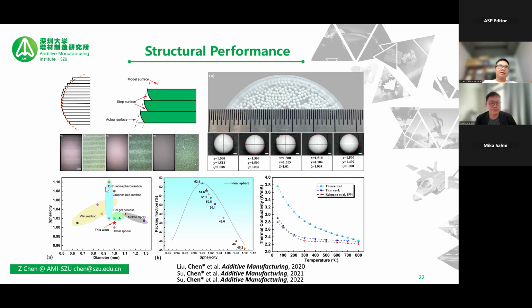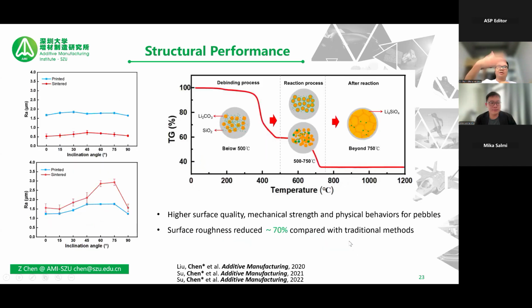For example, the staircase effect can be largely reduced, and surface roughness reduced by over 70% compared with the conventional method or previously reported 3D printing methods. And we are currently working on the reaction principle and seeing how it changes the surface roughness. Of course, there are some basic evident principles, like there is liquid phase coverage during the high temperature sintering. Then we are still working on that and seeing how it can improve the final results.